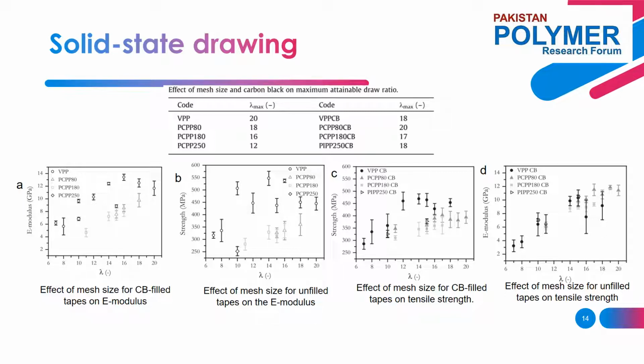The addition of carbon black to recycled isotactic polypropylene shows the opposite effect. In a polyethylene and isotactic polypropylene blend, the carbon black resides in the polyethylene phase without significantly affecting the viscoelastic or thermal properties of the blend. In the solid state drawing process, this results in better process stability by improved stress transfer between the isotactic polypropylene matrix and the PP contaminants. The addition of carbon black to recycled PP resulted in a higher attainable maximum draw ratio for recycled isotactic polypropylene.